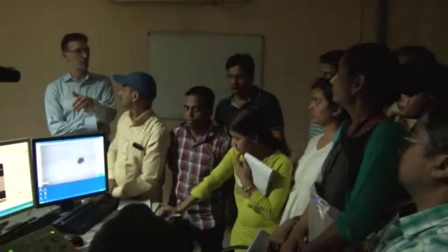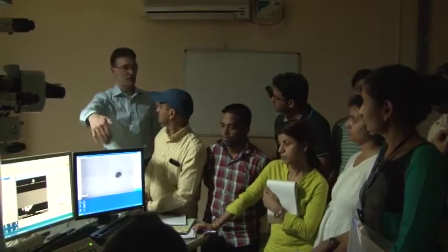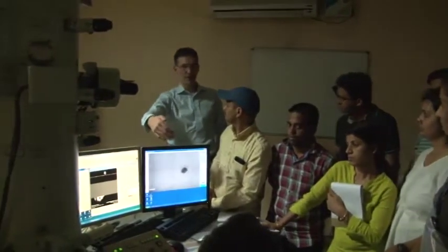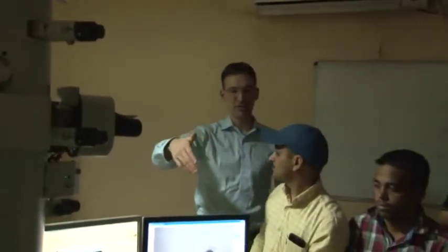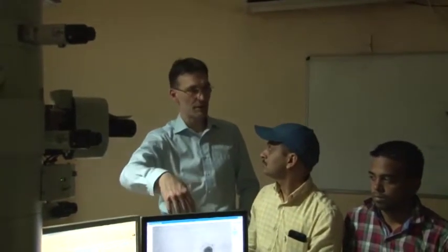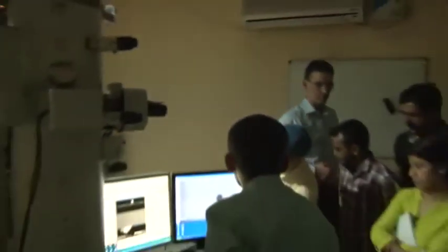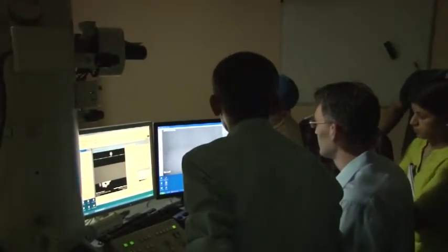Correct, yes. For atomic resolution imaging, we would calculate in live view the Fourier transform of the atomic resolution image, and we will come to the transfer function next week, how an atomic resolution image forms. In the Fourier transform of the recorded image, you see far better the twofold astigmatism to correct for, than just with these fringes. I don't know if it is possible to choose a window or like that, but I see here already a T, so maybe we can just